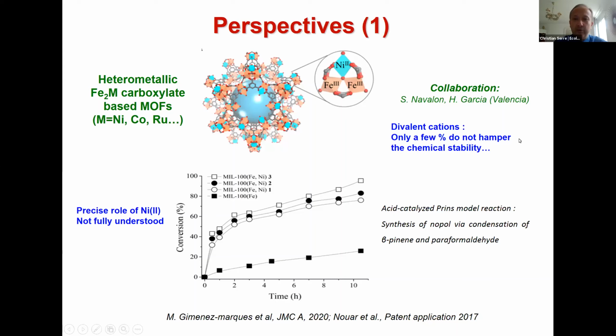First of all, you need to know that if you have too much nickel or cobalt in a trivalent-based MOF, then the chemical stability at some point will drop. We have seen that if you have 2 to 5%, then it's okay. The chemical stability does not change. But if you have 1 nickel for 2 iron, then the sample is no longer stable for a long time in water. With 2% to 5% of nickel, we collaborated with a group in Valencia in Spain.